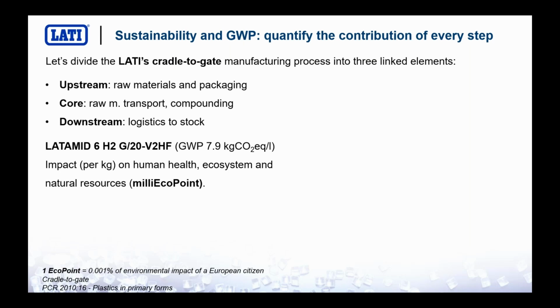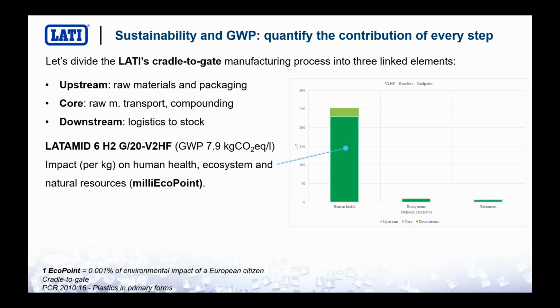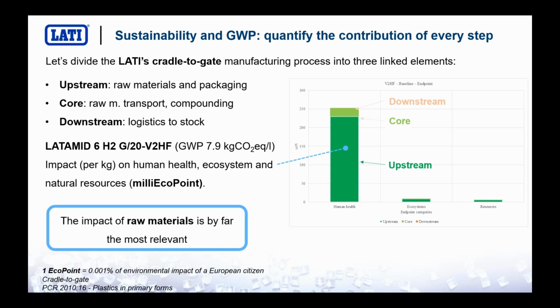It is possible to evaluate how every stream impacts this global warming potential, and what is found is that the biggest portion of this impact is due to the upstream. So the biggest portion of the global warming potential of 1 kg of this very material is related to the production of raw materials. The biggest issue is coming from the production of raw materials, not from extrusion or transport. It is the production of plastic in itself that is harming the environment.